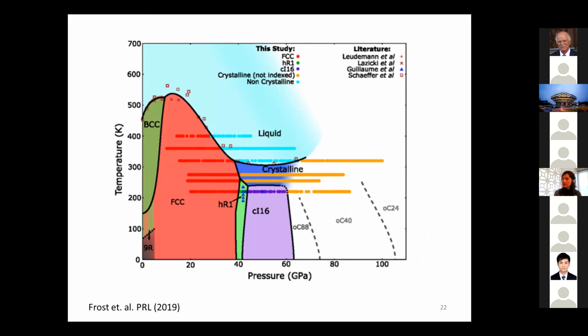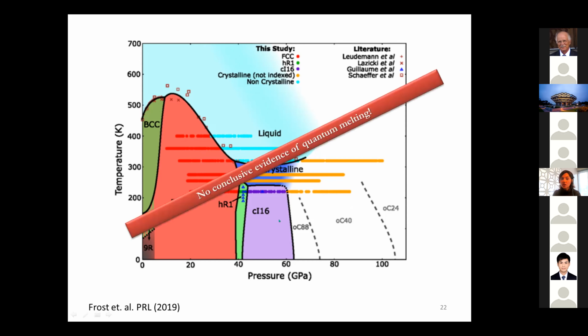Yes, it has a melting line that has a maximum, and it's at pretty low temperature. It goes to room temperature at 500,000 atmospheres, but it's also going through all these structural symmetry-breaking phase transitions. So we cannot say the lowering of melting is initiated by the quantum effects, but it could originate from the difference in the energetics of these low symmetry phases and the liquid, so the melting temperature goes down. Okay, so this is a pretty entangled place. Everything is entangled, the electronic effect, the lattice effect, everything is getting together.